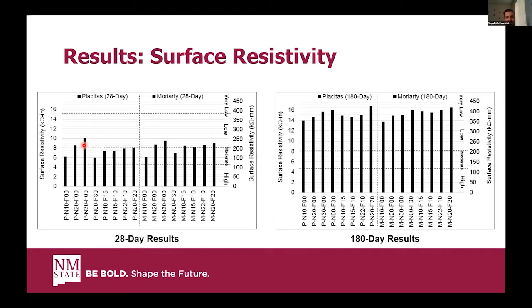But the more important point here is that in the 28-day results, you can see that the permeability of the mixture with 30% fly ash was much more than the permeability of the mixture with 30% natural pozzolan. But when we did the test after 180 days, we saw that the permeability of the mixture with 30% fly ash was really close to the permeability of the mixture with 30% natural pozzolan. This obviously can be justified by the slow reaction of the fly ash.